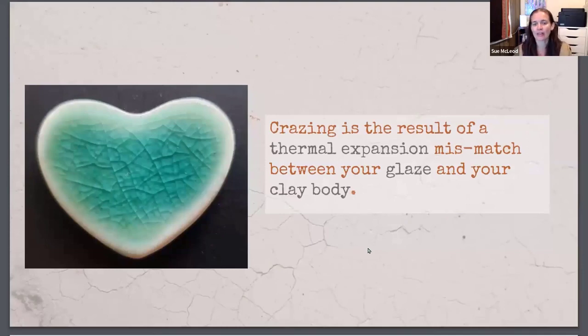It's the result of a thermal expansion mismatch between your glaze and your clay body. When we put our pieces in the kiln, the glaze expands as it's heated and contracts as it's cooled. And the clay body also expands as it's heated, contracts as it's cooled. If they do that at the same rate, we have what's called glaze fit, and we won't get this crazing effect. If our glaze has higher thermal expansion than our clay body, that's when we end up with crazing.